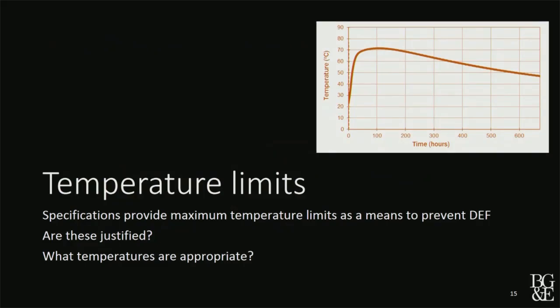Now you may wonder why I'm back talking about delayed ettringite formation. I thought I'd left that subject 20 years ago. But it turns out to be important when you're actually trying to place mass concrete. Because in mass concrete, what happens is the concrete develops heat. And we're now having to match temperature limits that are being assigned by the specifying agency that may make it very difficult to place the concrete.